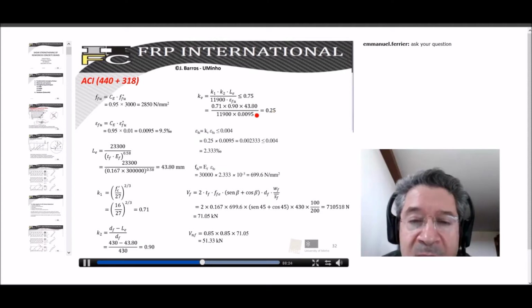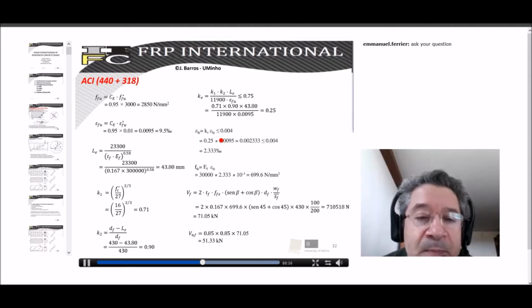This means that the effective strain should be 25% of the ultimate strain, and then we obtain a value that is about 2.3 per mile, that is lower than the maximum limit imposed by ACI, that is 4 per mile, and then we should use this 2.3 per mile. And we are now able to evaluate the effective stress, that is the product of the Young's modulus by the effective strain, and then replace in the equation that provides the contribution of the FRP system.